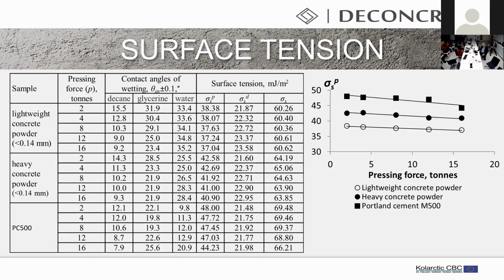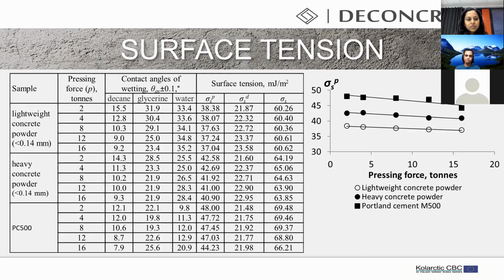The similarity of the values of the components of the surface tension can be used to characterize adhesion of inactive mineral powder systems that can be used as a filler in cement composites, polymer composites, and so on. And we measured the surface tension of concrete powder, lightweight and heavy concrete powder. And it's a lot similar to Portland cement, but heavy concrete powder is even more similar to Portland cement. And the main conclusion from that is, heavy concrete powder will have more adhesion in different mixes, new cement mixes.